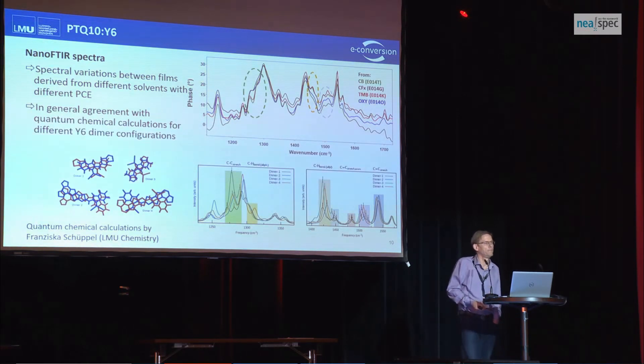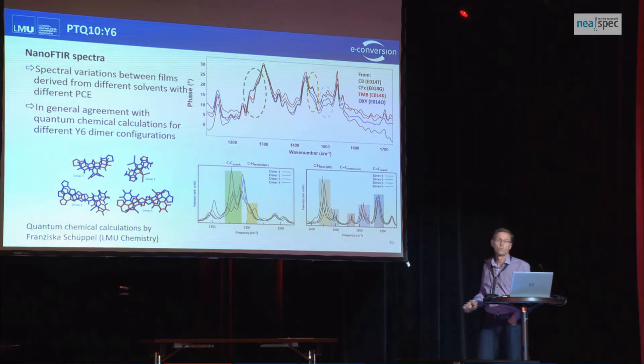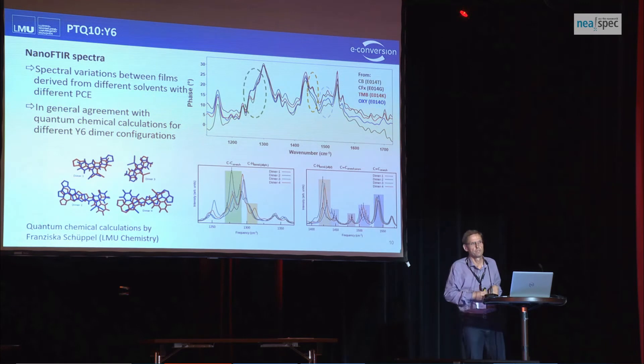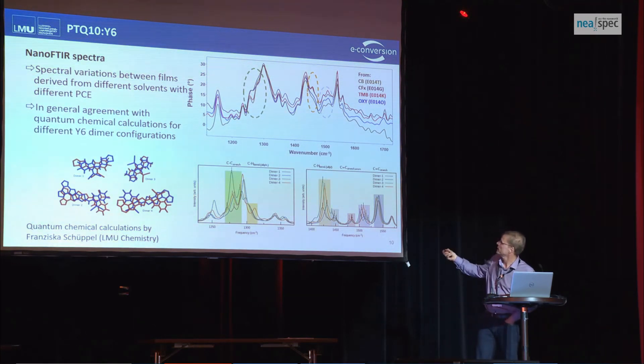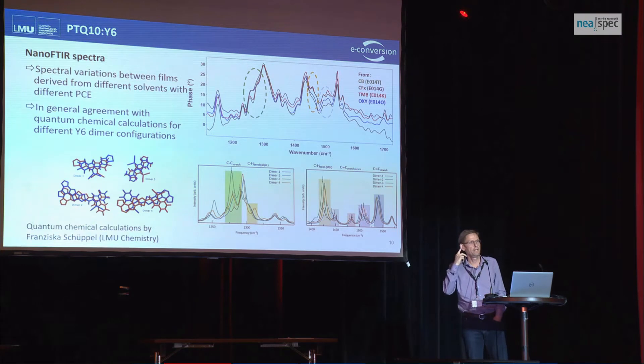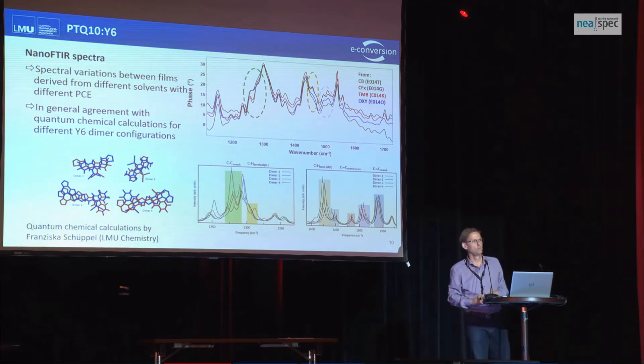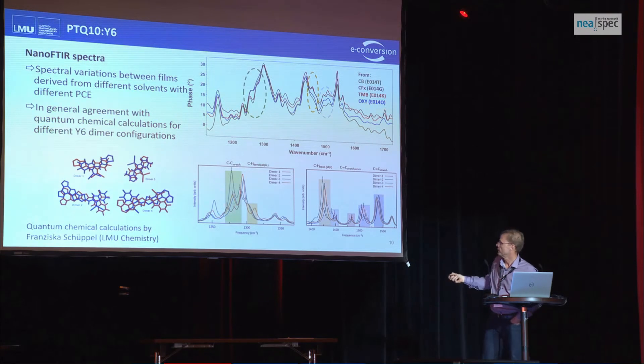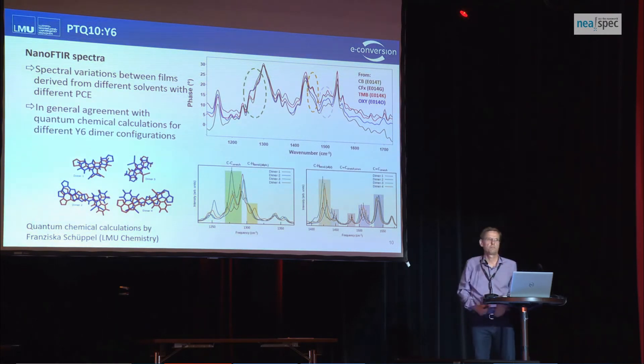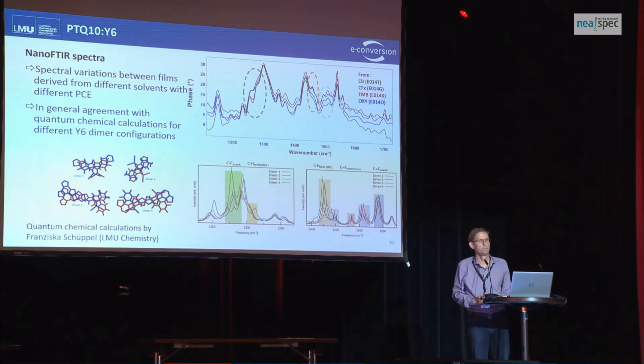What we do see are variations in the nano FTIR spectra for samples derived from different solvents. A list of four different solvents leads to different morphologies, different power conversion efficiencies, and some variations in spectral signatures on the left and right sides of the main peak. Our collaborators at LMU chemistry did quantum chemical calculations for different dimer configurations taken from crystallographic data, showing that from a theoretical point of view one would also expect variations in IR spectra for different local morphologies. This is compatible with what we see, but we don't see a clear correlation with film morphology.